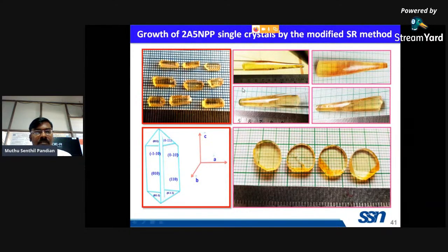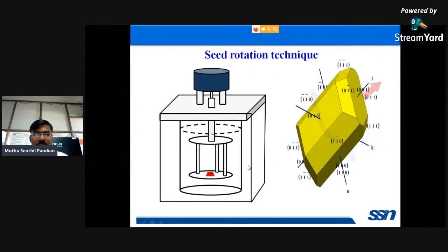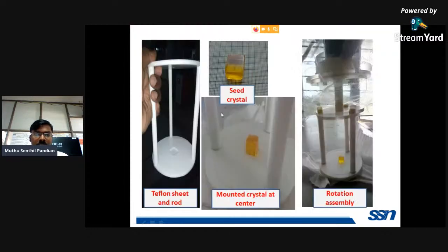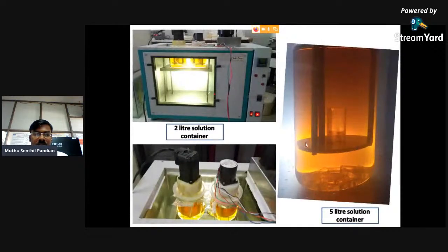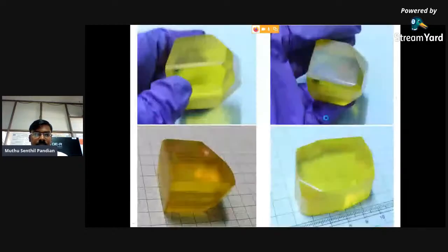This is the conventional method grown crystal. This is the SR grown crystal. These are cut and polished wafers. And this is the point seed rotation technique. We have chosen this 4-nitrophenol derivative single crystal for SHG direction. We have mounted a small thin plate-like seed crystal on this platform, poured the 5-liter solution, rotated it clockwise, and grown the crystal along its phase matching direction.